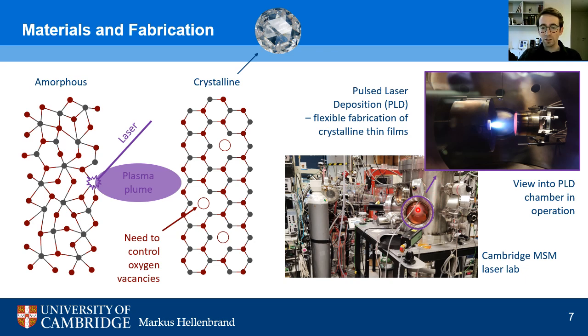And if we look into the window of this vacuum chamber, we see the process happening as in this zoomed in version here. So what we're doing is that we shoot high energy laser pulses onto an amorphous target, so a disordered material, such as here on the left, and the high energy of the laser will evaporate part of this material into a plasma plume. You can see this in the photograph here on the right.